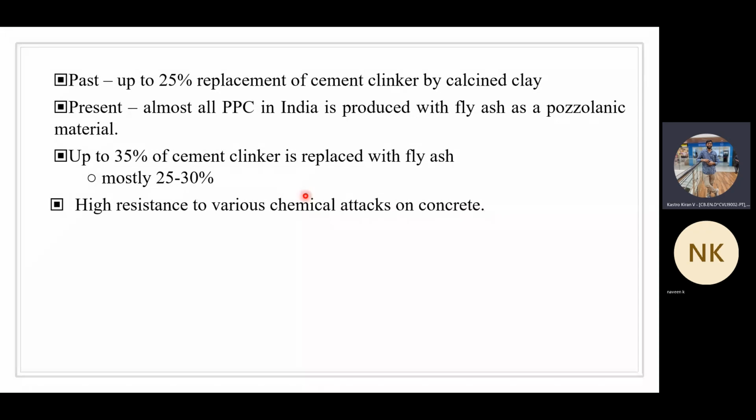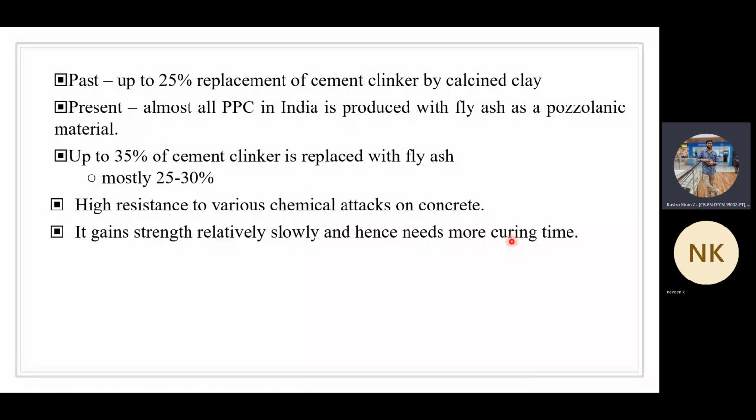So that is what it says. It gains strength relatively slowly, and hence it needs more curing time. That relatively slow duration is 56 days. So when you use PPC in construction, make sure you do the curing process for more than 28 days. Maybe you should go up to 40 or 45 days also. It's better if you go up to 56 days, but at least 40 to 45 days is required. That's something which we have to remember.